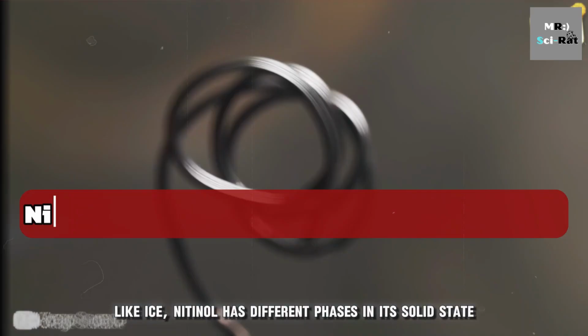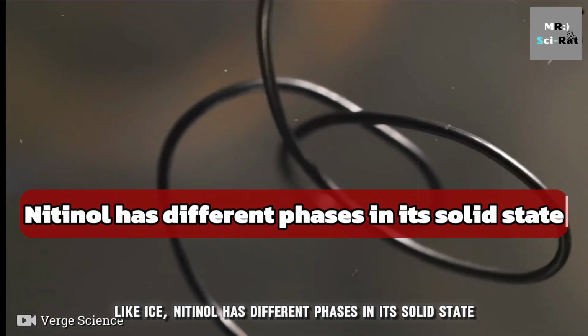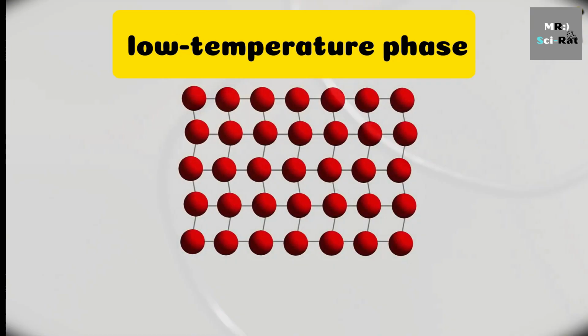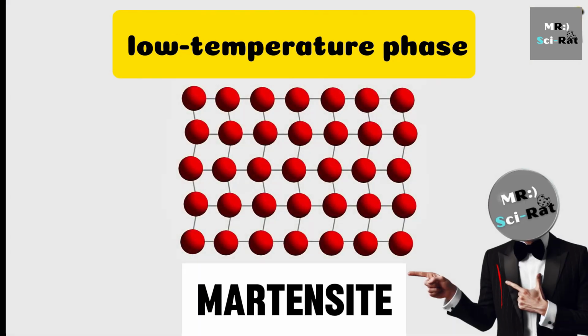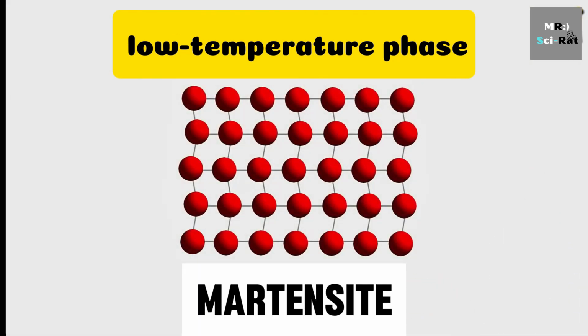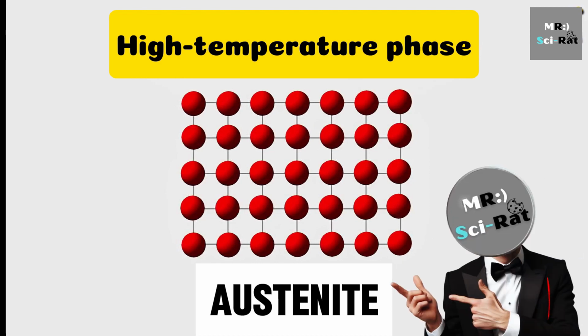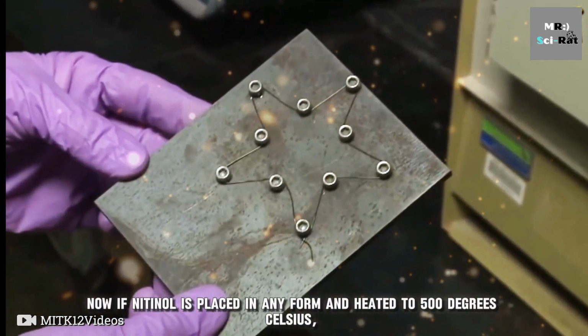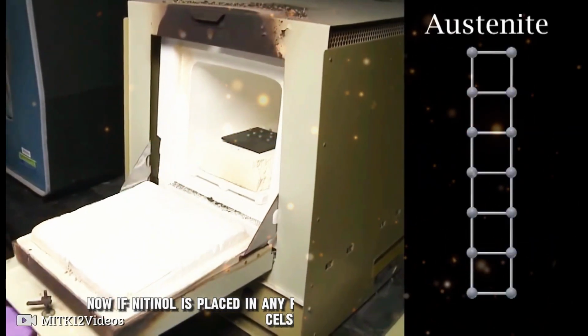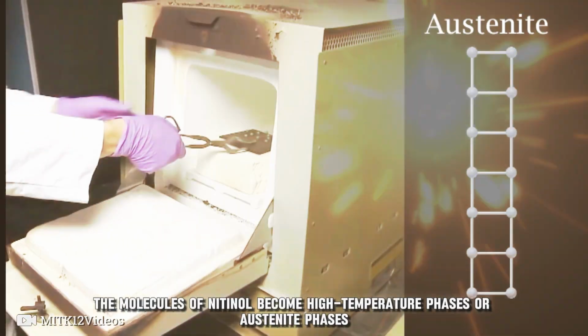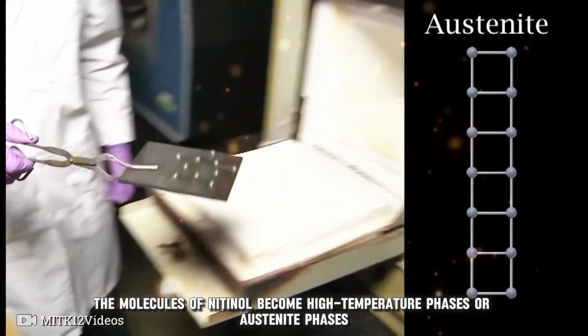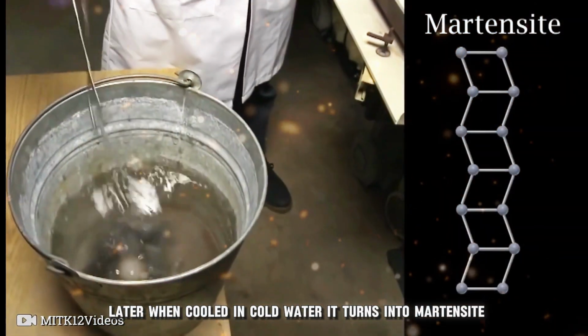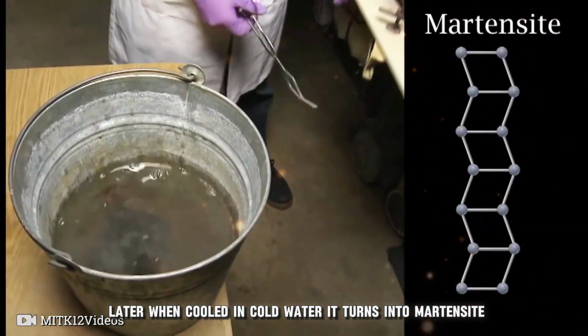Like ice, nitinol has different phases in its solid state. One of these is the low temperature phase called martensite. When the temperature increases, a high temperature phase called austenite appears. Now, if nitinol is placed in any form and heated to 500 degrees Celsius, the molecules of nitinol become high temperature phases or austenite phases. Later, when cooled in cold water, it turns into martensite.